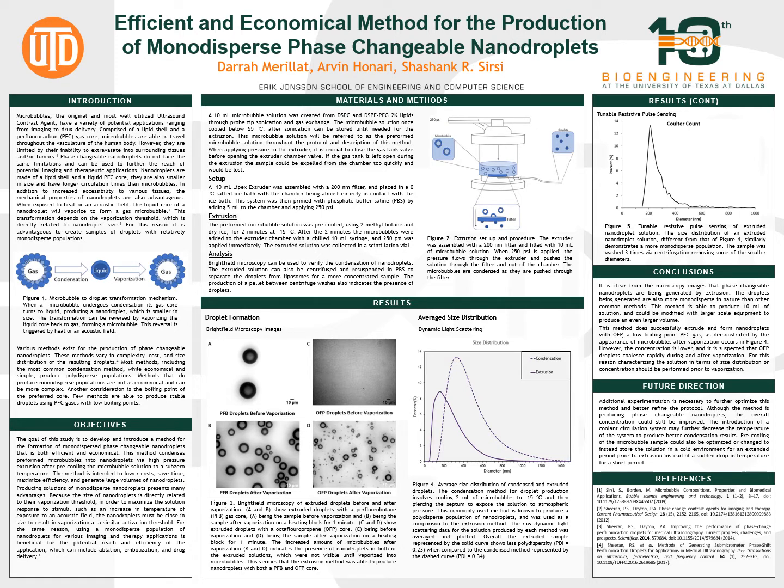That pre-formed microbubble solution is pre-cooled at negative 15 degrees Celsius for 2 minutes, immediately put into the extruder chamber, and immediately 250 psi is applied. This pushes the solution through the filter and out of the extruder. As it goes through that filter, the microbubbles are compressed down into nanodroplets. So that solution that is collected is then ideally the monodisperse solution.